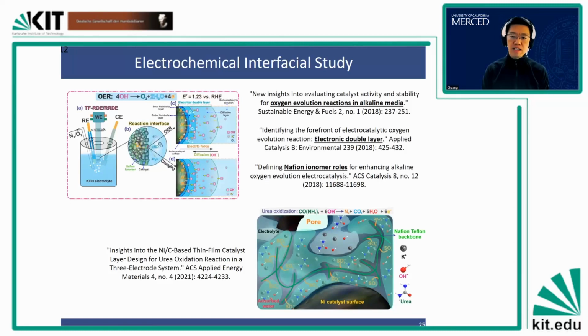So we actually apply this in alkaline oxygen evolution and also in alkaline oxygen reduction reaction. Some of the catalysts that we developed for this nickel-based material, we also apply them in a hydrogen evolution study. So we also have some preliminary results for that. If you're interested, we can certainly share those results with you later after this presentation.